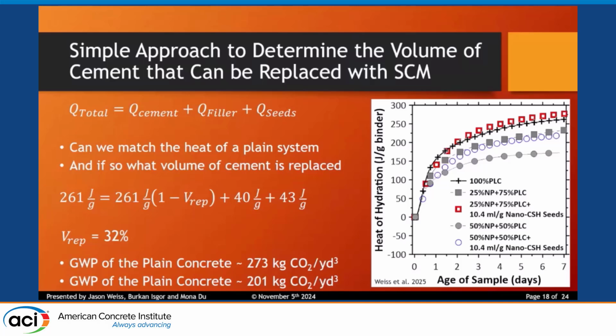I want this total heat because that's what I had from a pure system. I can take the amount of cement that I'm replacing. I can look at the amount of heat that's coming from the filler, the average heat that's coming from the seeds, and I can calculate out the volume replacement. Now, if I take out 32% of my clinker and I replace it with the seeds, and yes, the seeds do have their own global warming potential, but it's on par with cement and you use substantially lower amounts of it. I'm able to save about 70 kilograms of CO2 by doing this and having a very similar heat of hydration response, very similar early age strength development.